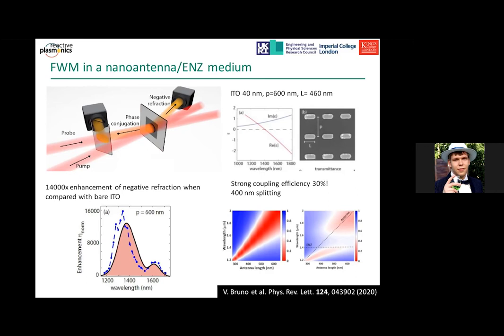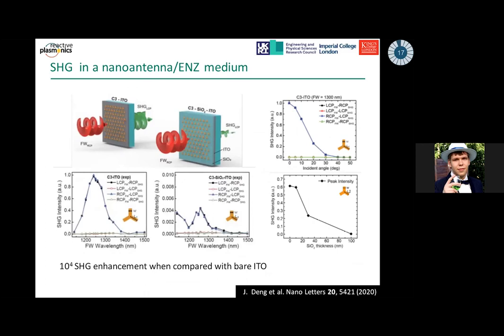A similar idea was used to demonstrate the enhancement of second harmonic generation on an ITO film coupled with an array of triangular plasmonic antennas. For the triangular system, the symmetry dictates that the second harmonic generation will be symmetry allowed even at normal incidence. And more than that, the circular polarized fundamental will only create a circular polarized second harmonic with opposite helicity. And that's exactly what we observed in the experiment. Left circular polarized fundamental gives rise to right circular polarized second harmonic and vice versa, enhanced in the vicinity of the epsilon near zero condition.